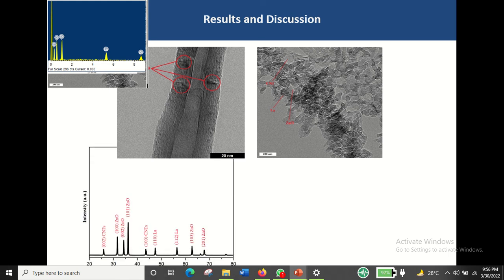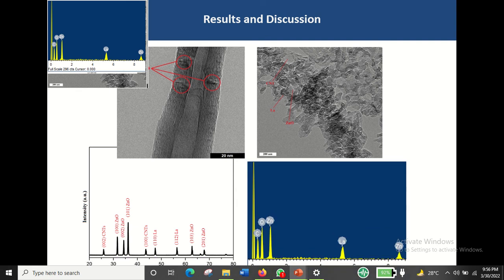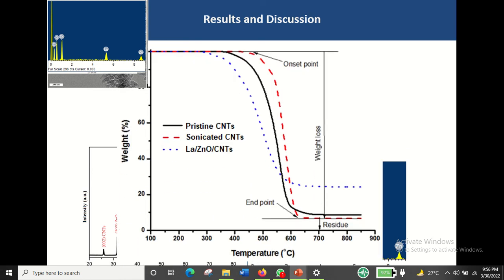Then we conducted the XRD analysis to confirm the planes of the constituent materials in the photocatalyst. The XRD results clearly showed the presence of the planes of the carbon nanotubes, zinc oxide, and lanthanum. And then we checked the composition of the constituents using the EDX analysis, and these analyses confirm that the carbon, oxygen, zinc, and lanthanum are present in the composite photocatalyst.